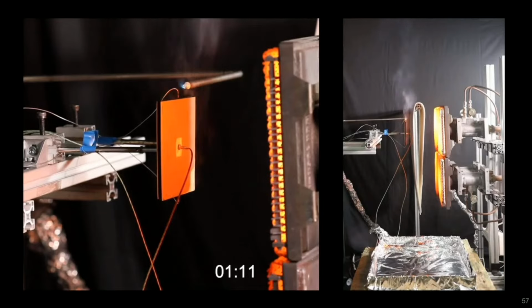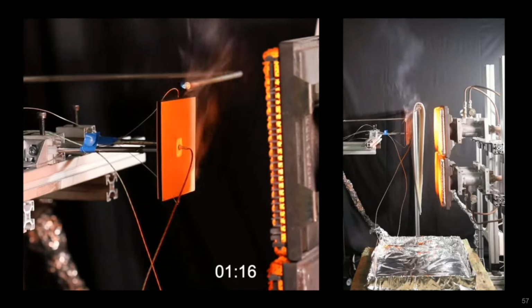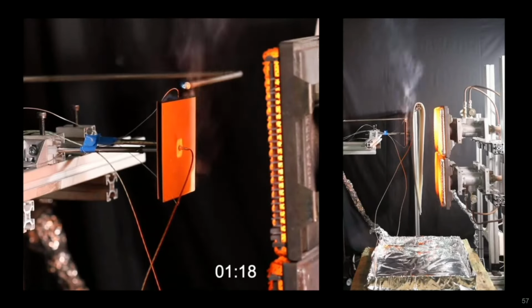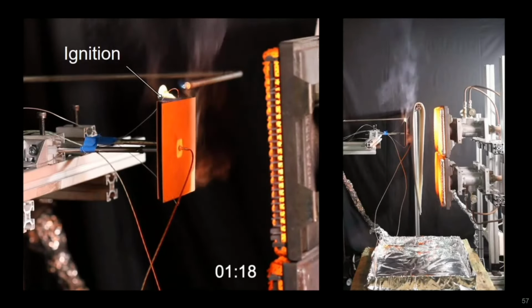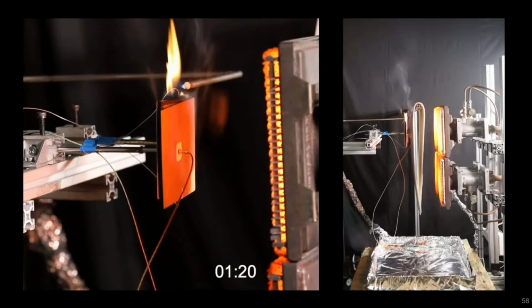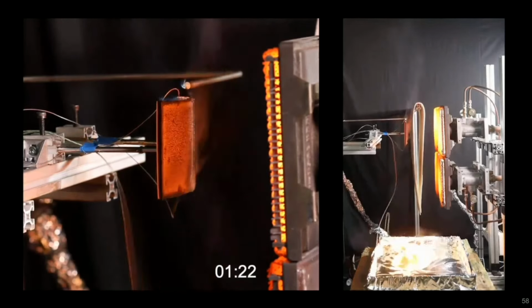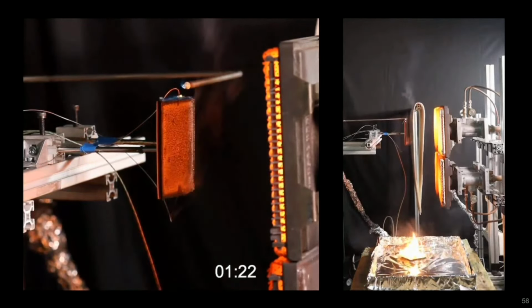Keep that playing. At 1 minute and 18 seconds, we'll see ignition occur at the top of the sample. There it is. And a few seconds later, at 1 minute and 22 seconds, the front facer of aluminium falls away from the sample and lands in the debris tray, and you can see that it's now flaming in the debris tray. The back face of the aluminium remains in place, held on the sample holder, and the majority of the polyethylene core material remains attached to that face of the sample.